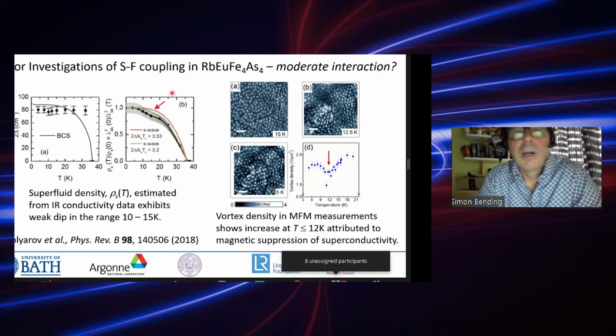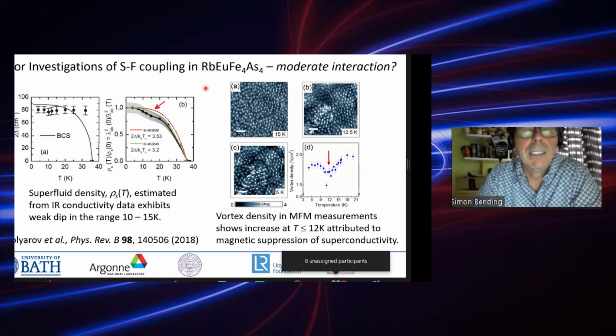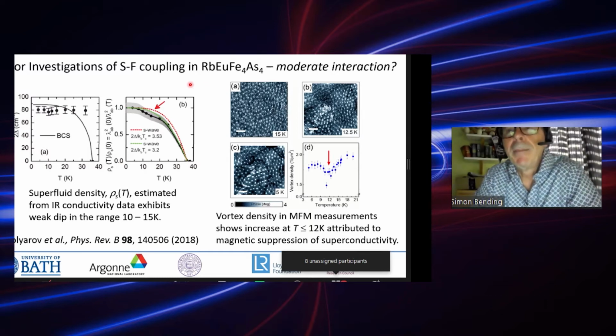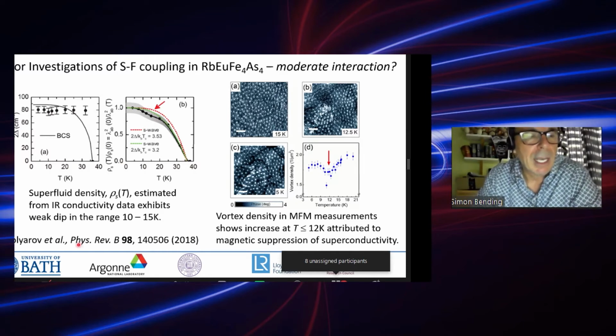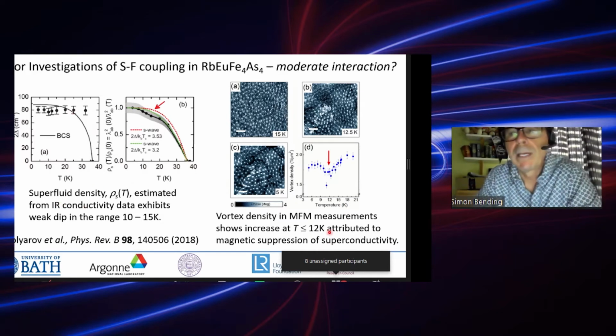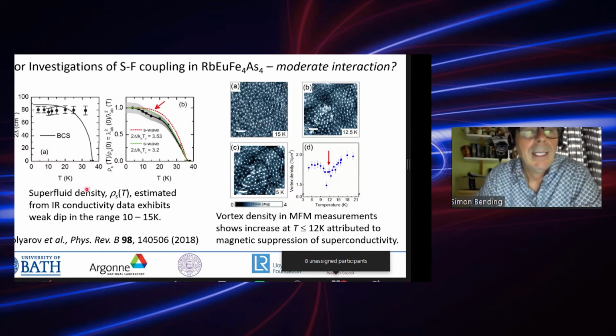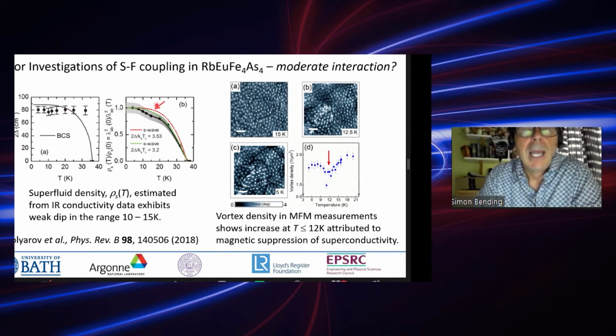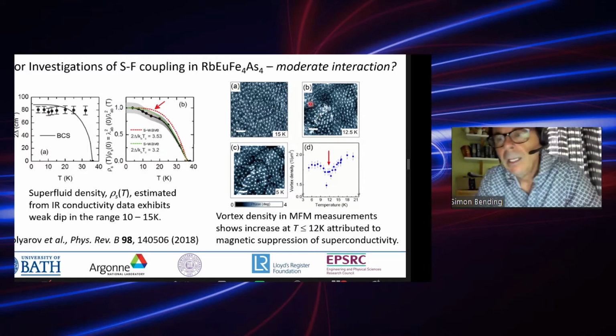So let's look at some of the prior investigations of this material. A number of groups have actually looked at the coexistence of superconductivity and magnetism in it. So here is a nice paper from Stolyarov et al., where they looked at 2 different things. They looked at the infrared conductivity in this material, and they also did magnetic force microscopy measurements of vortices in this material. From the IR conductivity data, they were able to invert these data and calculate the superfluid density as a function of temperature. And you can see a small but significant dip in the superfluid density around the magnetic ordering temperature of about 15 Kelvin.